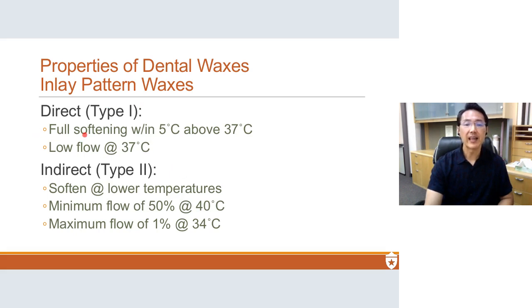In the direct case, you're forming the pattern inside the mouth. So you want full softening within 5 degrees above 37 degrees Celsius, so the patient does not feel uncomfortable. And at 37, when you're in the mouth, you don't want it to flow much at all, so it holds its shape. Indirect, you want it to soften at a little bit lower temperature because you're going to make it outside, all right? And so they have slightly different flow properties, as you can see here, with respect to temperature.